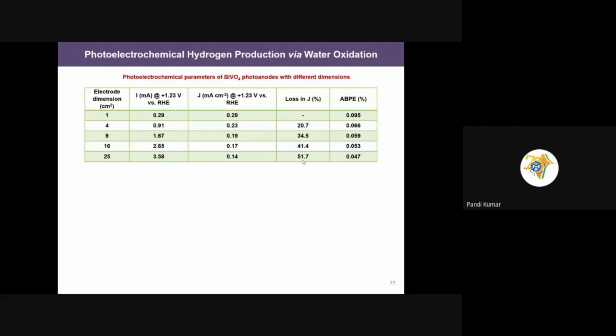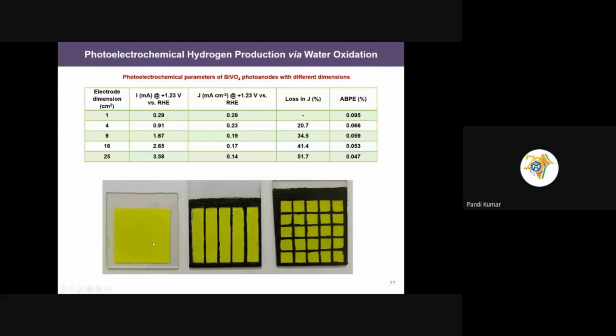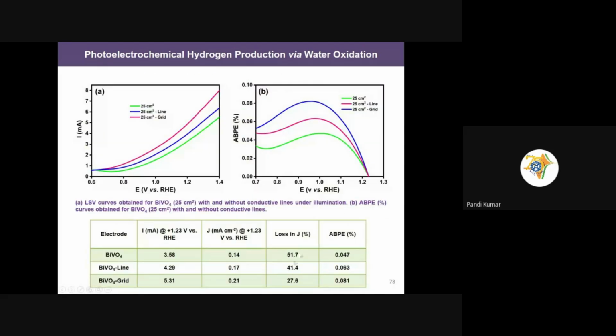After we modified the pattern, this is the 25 centimeter square. But 1 centimeter square shows the higher activity. If we use the plain one, the high charge transfer resistance and charge recombination bring down the efficiency below 50%. So we modified the electrode fabrication, making a line pattern and a grid pattern. This will act as 5 electrodes, and this will act as 25 electrodes, or 25 one-centimeter-square electrodes integrated like that. Accordingly, we performed the experiment. Now you can see that when we use the plain electrode, there is a 51% loss.